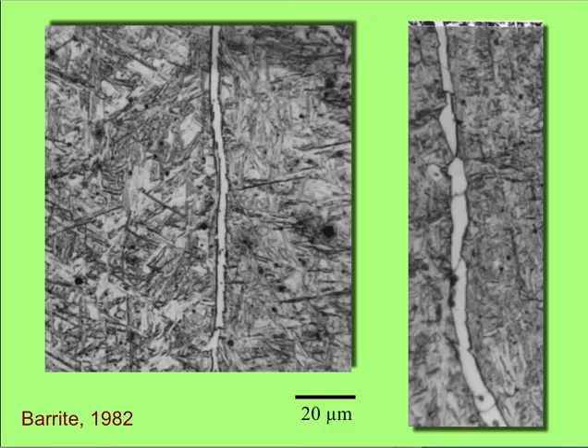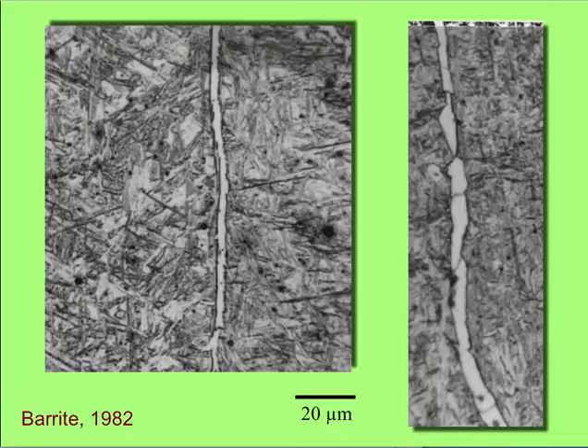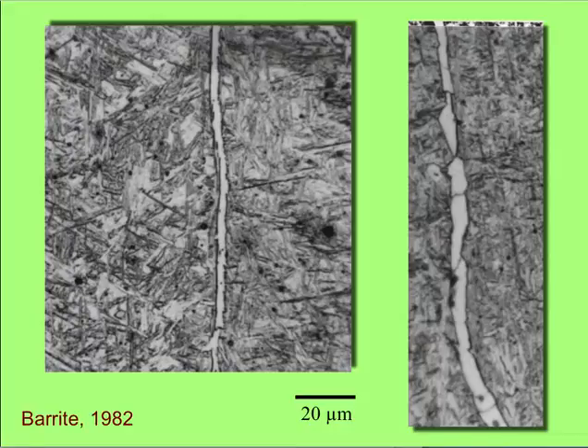We have these thin layers of ferrite at the austenite grain boundaries and we want to work out the kinetics of the growth of those layers. We do not want these layers to be too coarse because there is no structure in them - if you have a large region of ferrite without any structure, you basically get cleavage cracks propagating without any deflection at all. I want you to close your notes and we want to work through how to treat diffusion-controlled growth.